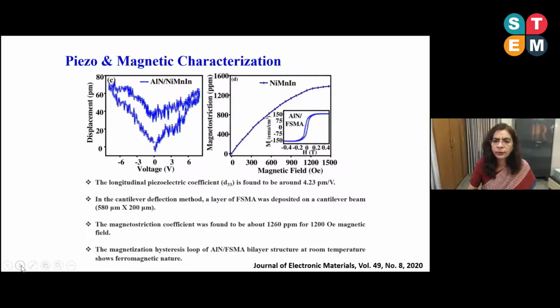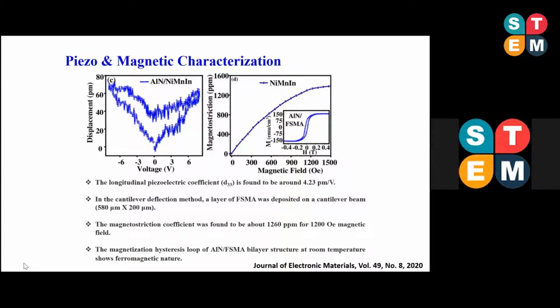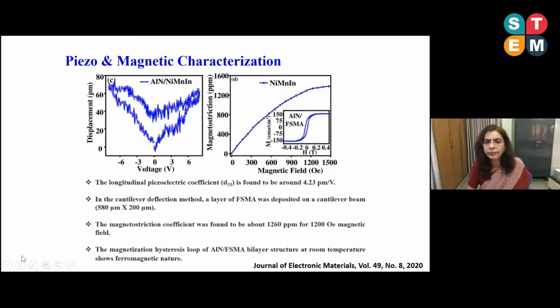So here we tried to measure the piezoelectric coefficient at D33, which was found to be 4.23 picometer per volt in this case. FSMA was deposited over the silicon cantilevers in order to measure the magnetostriction coefficient using the laser Doppler method, and the coefficient was observed to be 1260 ppm for 1200 Oersted applied magnetic field.